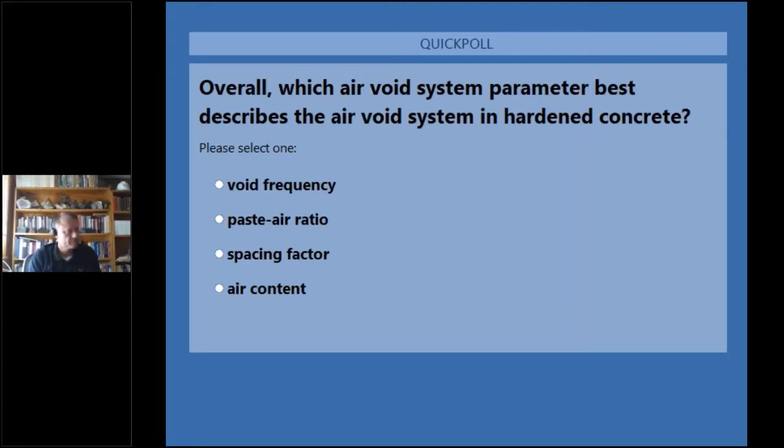All right, we do have a few others. Paul Griggs asked, how can you distinguish between voids from plucked aggregate particles or an air void? Yeah, great question there. So aggregate particles are typically more angular than they are spherical. So seeing a void that has definite sharp angular edges to it is a red flag for me that that's not formed from air or water. It was probably formed from a sharp piece of rock that plucked out.